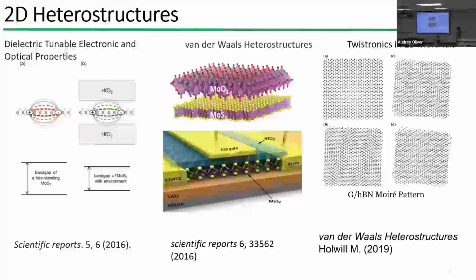And then we can also create a heterostructure with other 2D materials for various device applications. In a transistor, we'll have different interfaces, right? This is the semiconductor here, and you have oxide, and you have metal. So you have a metal-semiconductor interface and an oxide-semiconductor interface. The nature of those interfaces will dictate the device properties, and we can calculate that by looking into electronic properties like band offsets, band alignment, effective mass, mobility, and so on. And recently, people, instead of just making this kind of straight heterostructure, are twisting. By twisting, this is for graphene and hBN, you can see this kind of pattern, right? We call this a moiré pattern, and that has some exotic electronic properties